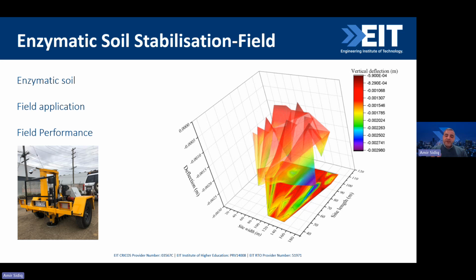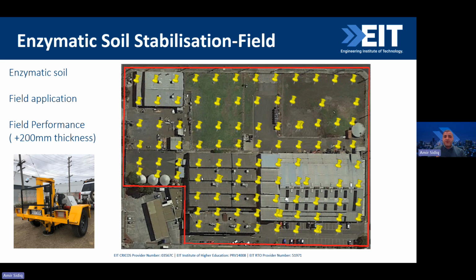Again, having a site of about 34,000 square meters, and we're talking about microns of deflection, we're looking at very precise information, very precise analysis across the entire site. So we saw some of these, and we have about 2,000 microns, and our aim was actually to get almost all of them across the site to less than 1.5 millimeter deflection.